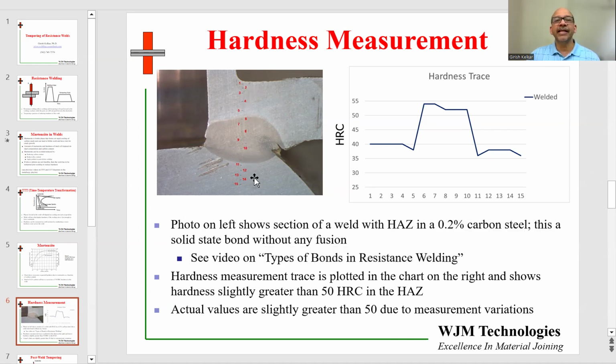So this weld was sent to the lab for a hardness scan, and starting from the top to the bottom, 1 to about 15 spots, and showing on the screen in the chart form on the right, you can see that the hardness in the heat affected zone, which seems to be the darker region over here, is now close to 50 or slightly above that. Whereas the base metal hardness is around 40 on one side and about, say, 37 or 38 on the other side. So you can see a distinct increase in hardness in the weld due to welding.